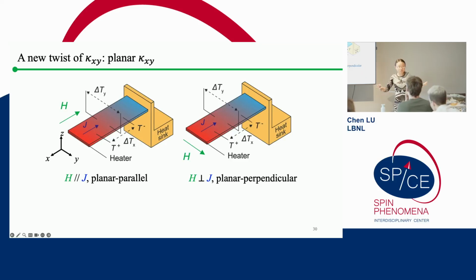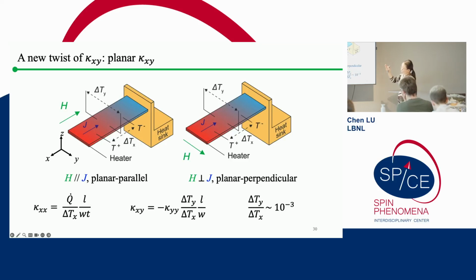So 99% it looks exactly the same as a conventional thermal Hall effect measurement. The only difference is the direction in which we apply a magnetic field. In a planar thermal Hall effect study, we can either put the field parallel to the heat current, or we can put the field and the current perpendicular to each other, but both lie within the sample plane. For conventional thermal Hall, you put the field perpendicular to the sample plane. So the only difference is the direction in which you put the field. With this experimental setup, we are able to measure both thermal conductivity and thermal Hall conductivity simultaneously. Everything in the setup looks exactly the same as before.